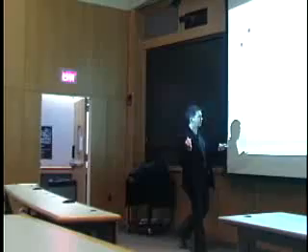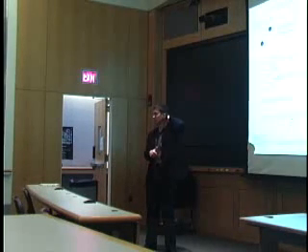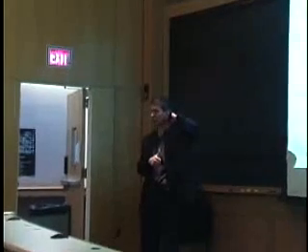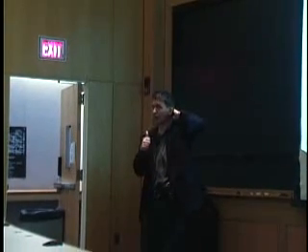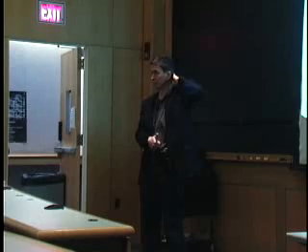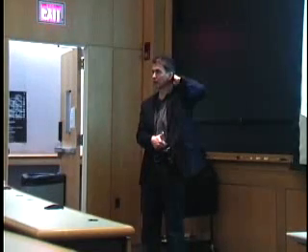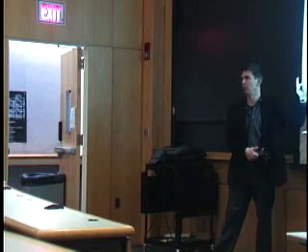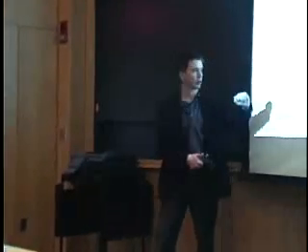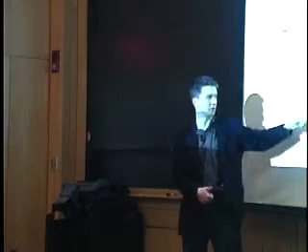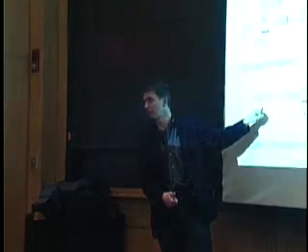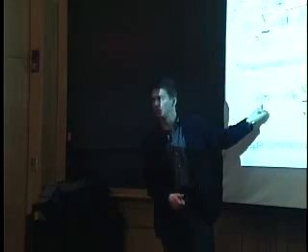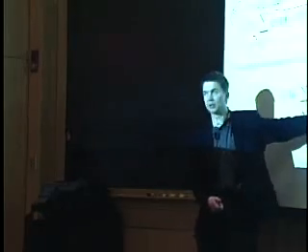So in this case, what should you do? In everything I showed you earlier this morning, I used the energy as the Hamiltonian. I used the direct DFT energy in my Hamiltonian. What I really should have used, to be correct, is the vibrational free energy. If I had used the vibrational free energy in that Hamiltonian, I would have gotten the full partition function, and therefore the total free energy of the system. So what did I do instead? I didn't calculate this. I approximated it by something.